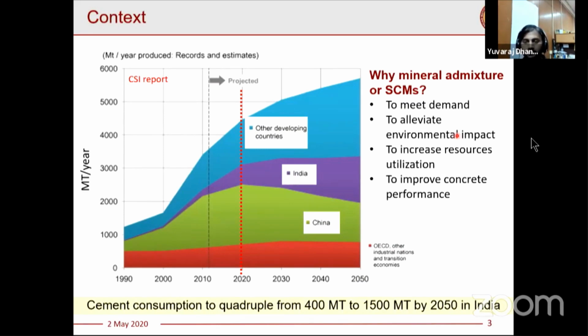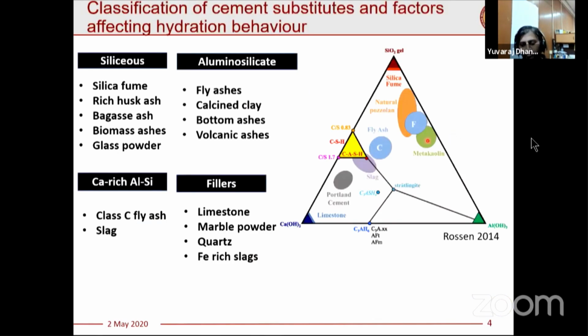contexts of application. Trying to give you a classification of different SCMs, I would put it as siliceous. So you can see a ternary chart of calcium, silica, and alumina. So these are the kind of SCMs which mainly have reactive silica alone in it. So you have silica fume which fits in right in there. You have vegetable ashes such as rice husk ash, bagasse ash, biomass ashes, even ground fine glass powder.